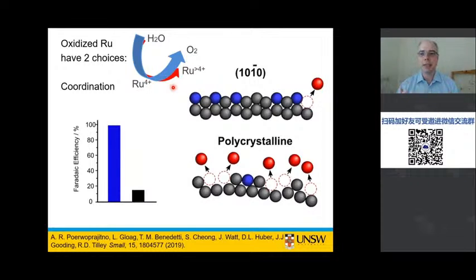If we have a look at the Faradaic efficiency of the oxidized ruthenium particles, when we have these low index facets, they actually have a very good Faradaic efficiency. That means that during the electrocatalysis, the oxidized ruthenium is doing a lot of catalysis rather than dissolving up into the solution. And if we have polycrystalline ruthenium catalysts, we have very low Faradaic efficiency because all of the energy that we're putting in is oxidizing our ruthenium, and then that's immediately dissolving into the electrolyte. So we don't have very good Faradaic efficiency at all. And if we want to think about why, well, it's quite understandable.